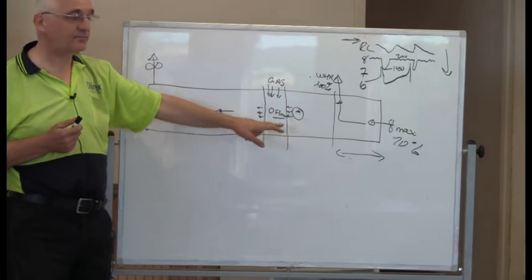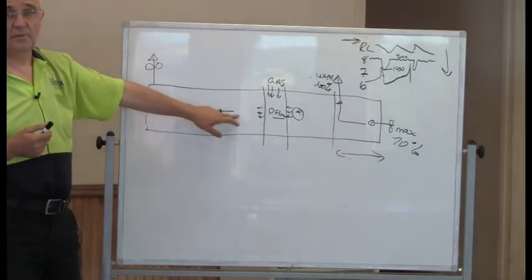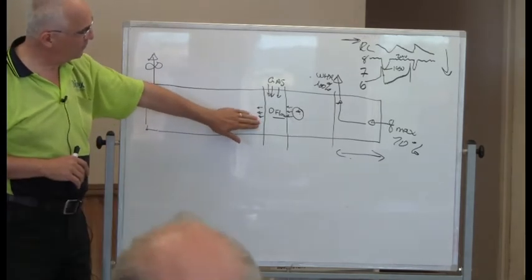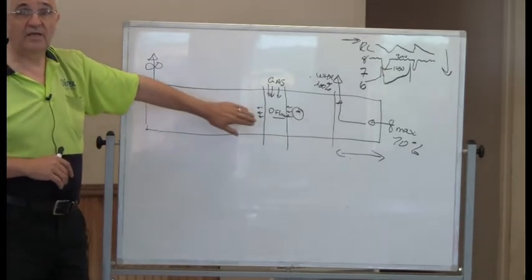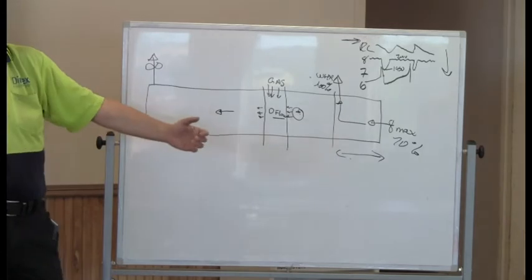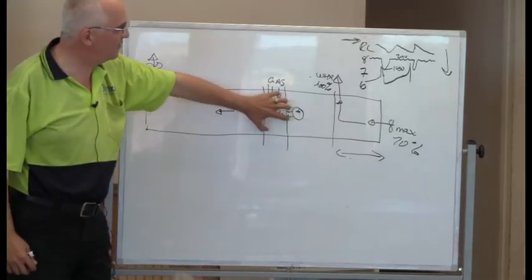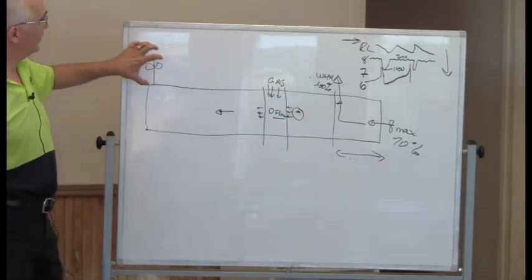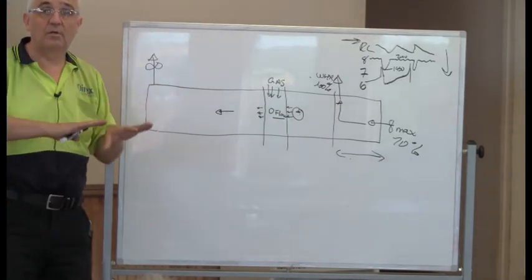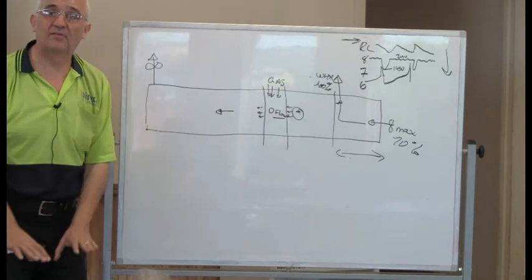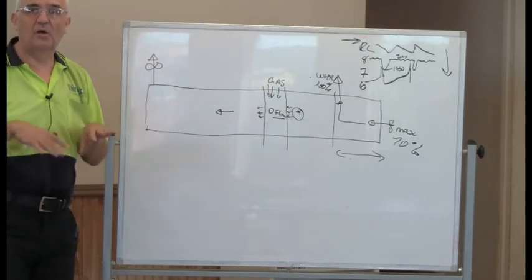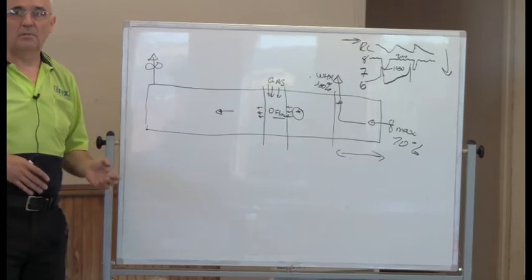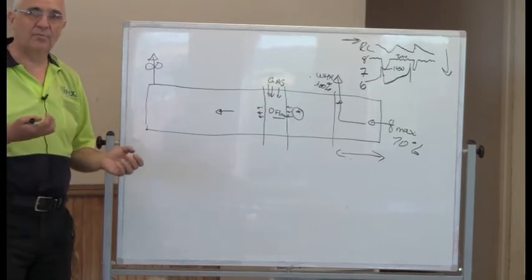And then the exhaust is just pulling enough to release the smoke that accumulates. You don't want to pull that, you actually move everything forward. This is probably the one that is going to work not at the minimum, but probably lower than what you normally run, just strong enough to pull the smoke.